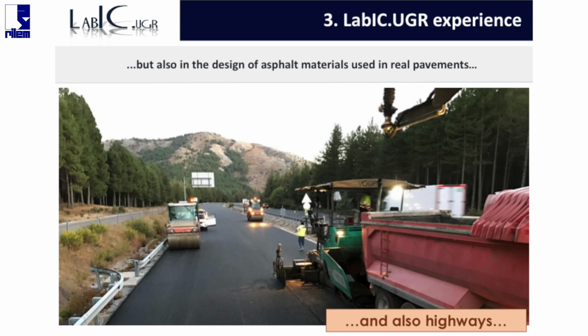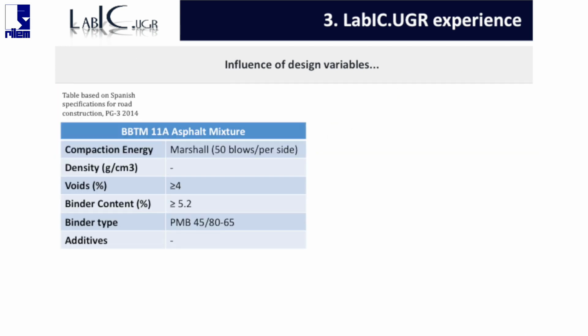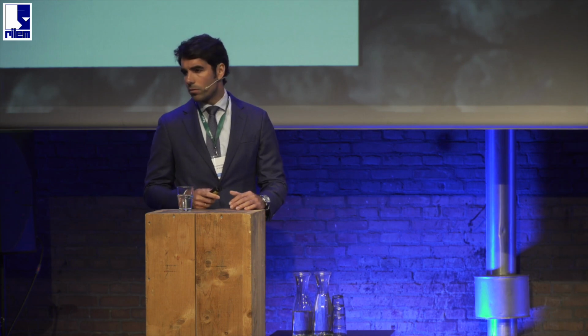Starting by the beginning, by the design stage in the laboratory, I will show you the sensitivity of this test to the design variables, such as the density, voids, binder content, binder type or the use of additives. For that purpose, I will show you an example with a BBTM mixture, which is a common mixture used in surface layer in highways in Spain. And a Spanish standard gives that recommendation to design it.